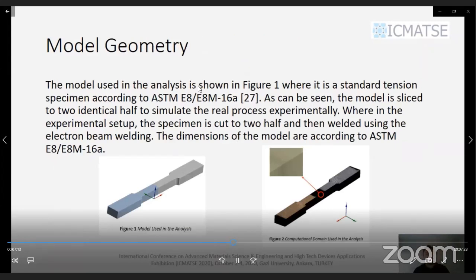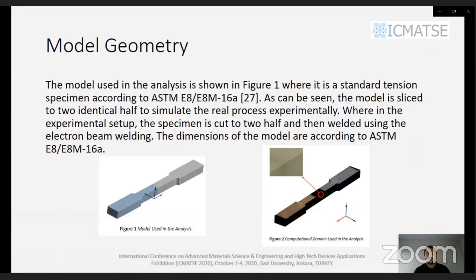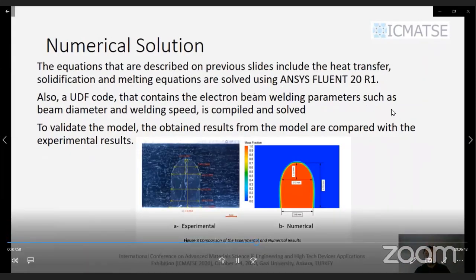Here is the model geometry section. The model used in the analysis is shown in figure 1, figure in below actually, where it is a standard tension specimen according to ASTM E8/E8M 16A. As can be seen, the model is sliced into two identical halves to simulate the real process experimentally. In the experimental setup, the specimen is cut into two halves and then welded using electron beam welding. The dimensions of the model are according to ASTM E8/E8M 16A. Here is the model I used.